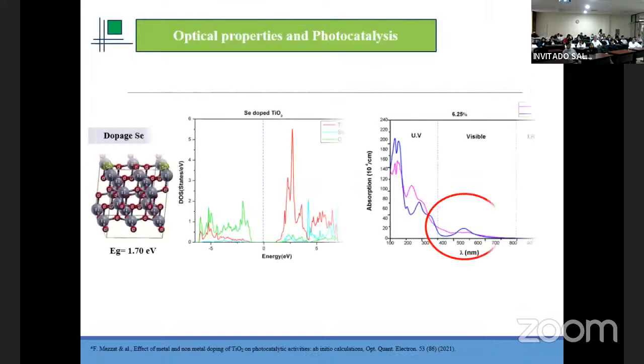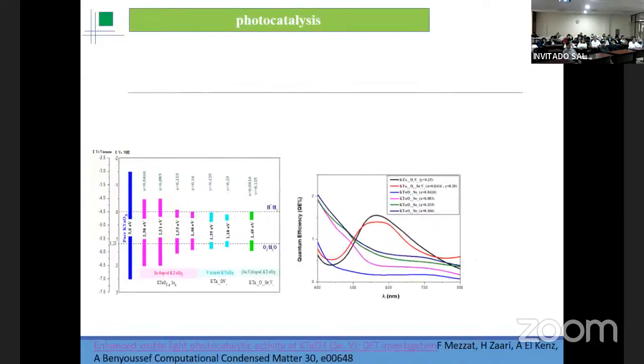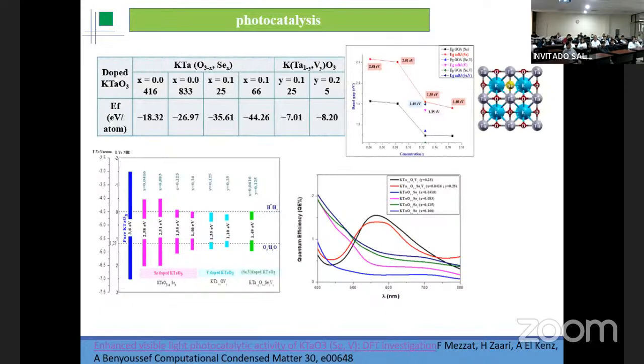As an example here, I present titanium oxide having a band gap of about 3 electron volts. And when we dope it with selenium, we get the band gap close to 1.7. That's good. And the absorption is shifted to the visible range. That's good also. Another example here, we have perovskite material. When we dope it with different materials, or co-dope it in different sites, we are looking for stability. As we can see, the formation energy is negative, the band gap is reduced, and the quantum efficiency is enhanced in the visible range. So we can see that doping is a key characteristic for this application.